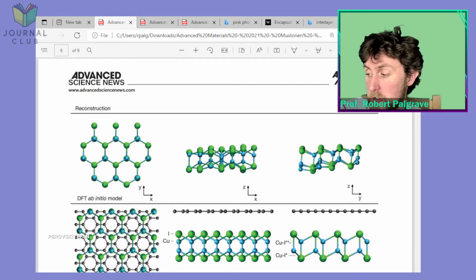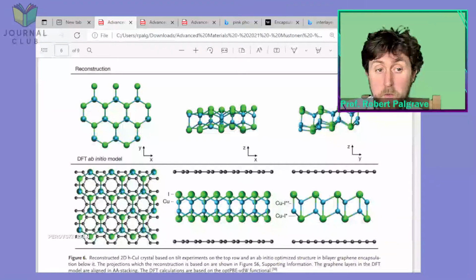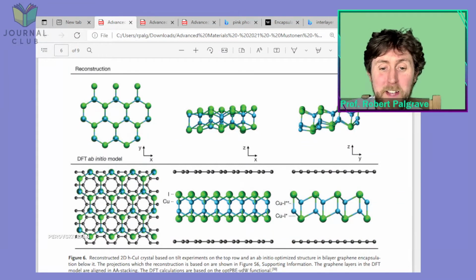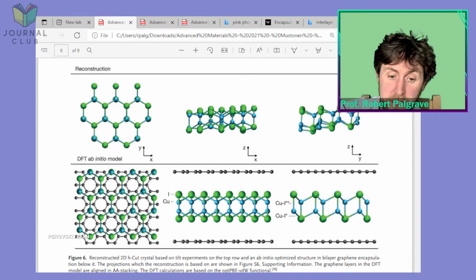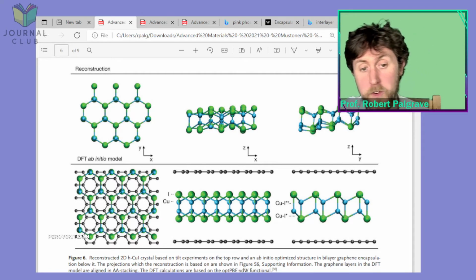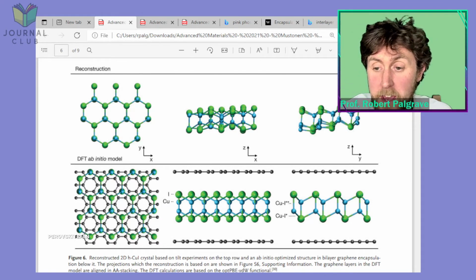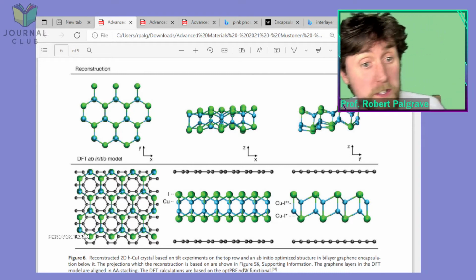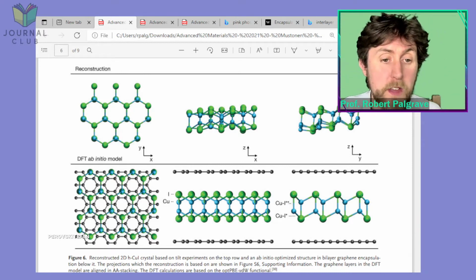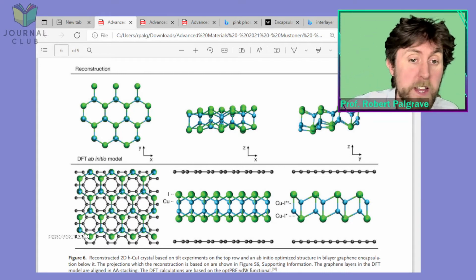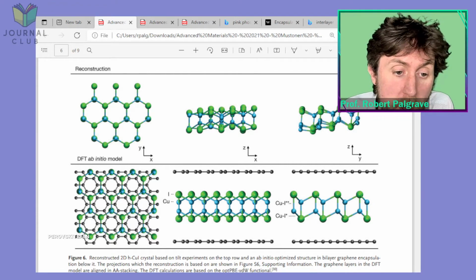This is the DFT, the bottom one. Yeah, I cut off the top part. Below is the DFT. So again, iodine is predicted to be stable on the outside, copper on the inside. That's kind of what they see here, and that matches up with the cross-sectional TEM and with the tilted TEM with the simulations we saw below. So this is nice as well.